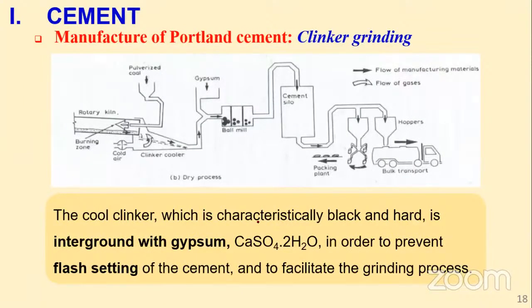So the clinker, we are saying, is a characteristic black, hard, and ground with calcium sulfate, which is gypsum, in order to prevent flash setting and also to facilitate the grinding process. So it means, as well as reducing flash setting later on when cement comes in contact with water, it's also helping in the grinding process.